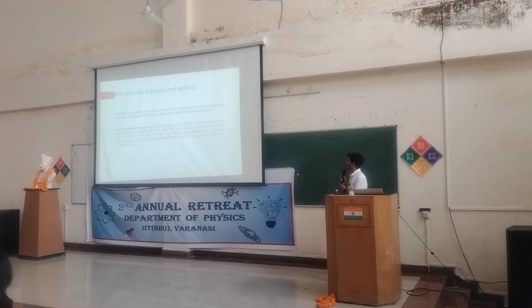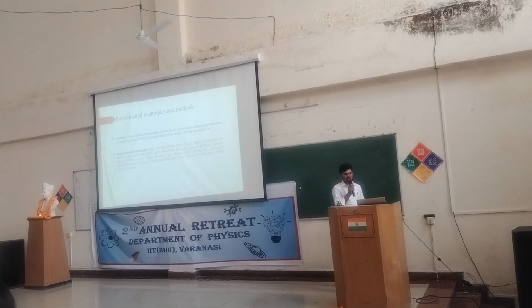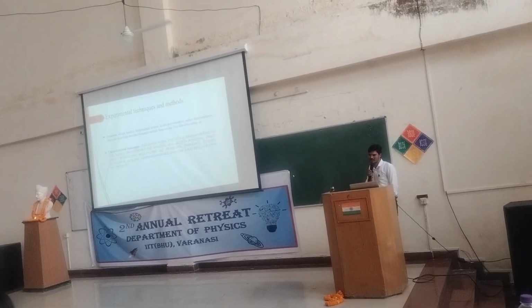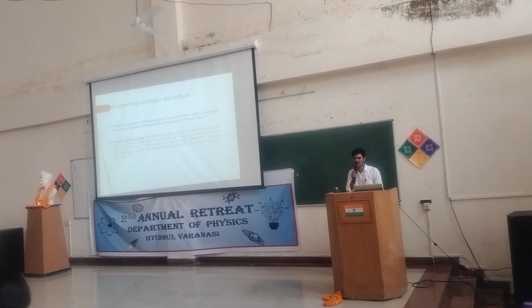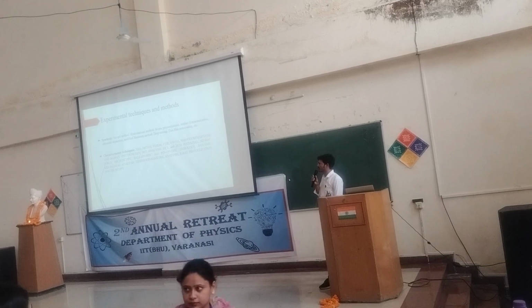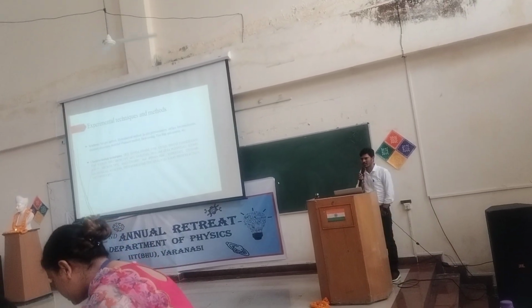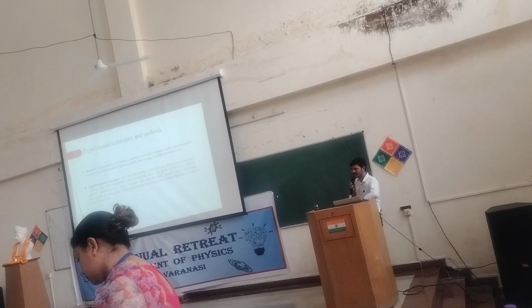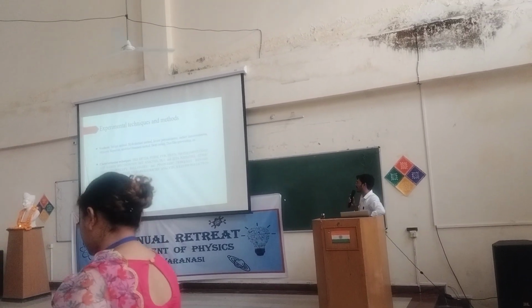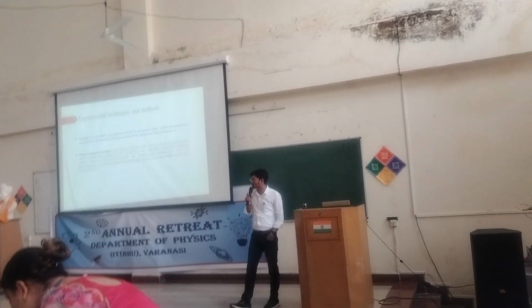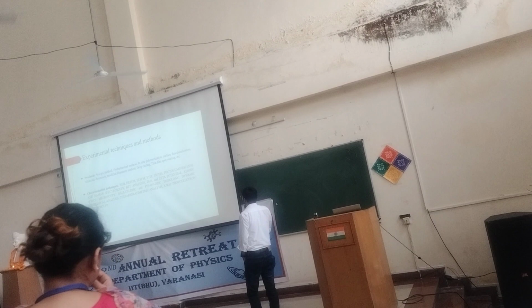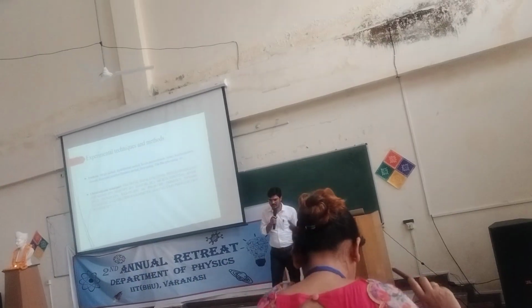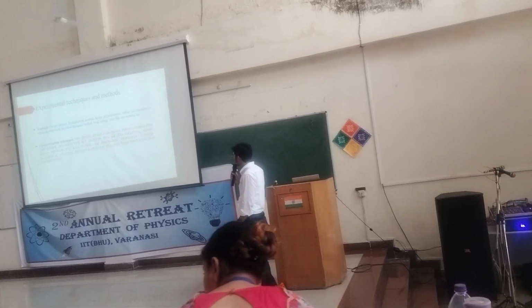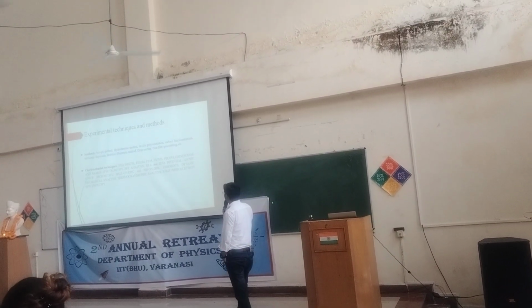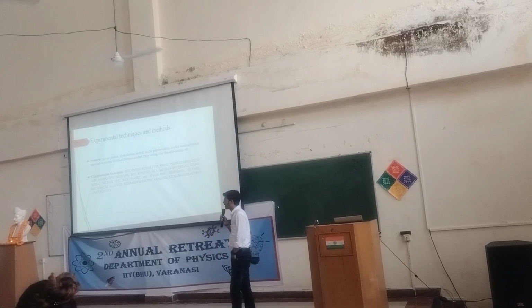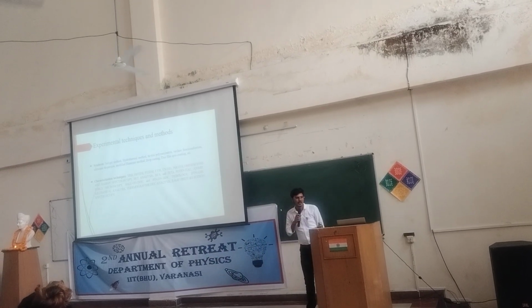And for the synthesis of these materials, we use techniques like sol-gel method, hydrothermal, in situ polymerization, surface functionalization, one of the parts of our research, ultrasonic dispersion, and modified Hummers method, drop casting, thin film, spin coating, etc. And after synthesis of the materials, we use the basic characterization like XRD, HRTEM, FESEM, FTIR, UV, and all those things. And for the application measurement purpose, we use ball-on-disc and pin-on-disc tribometry, dynamic mechanical analysis and thermogravimetric analysis, etc.